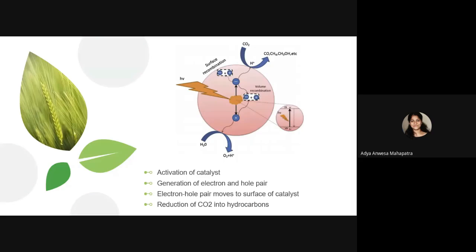The problem with this mode of artificial photosynthesis is that it is fundamentally a challenging process, as carbon dioxide reduction to carbon dioxide minus anion or carbon monoxide requires a very high activation energy. New electrocatalysts are being developed to reduce the activation energy of carbon dioxide reduction. We have an example. Partially oxidized atomic cobalt layers show a good result. However, efficient production of hydrocarbon remains a very difficult challenge till now due to the inefficient carbon dioxide reduction approach.